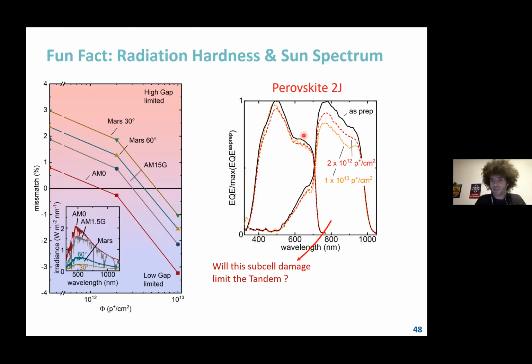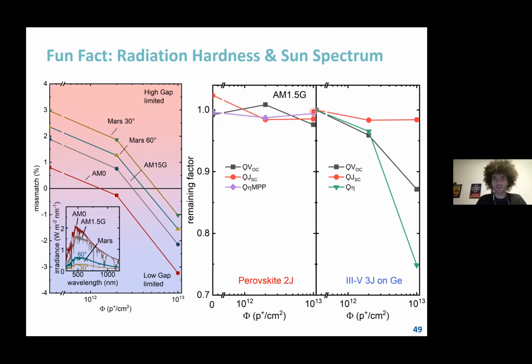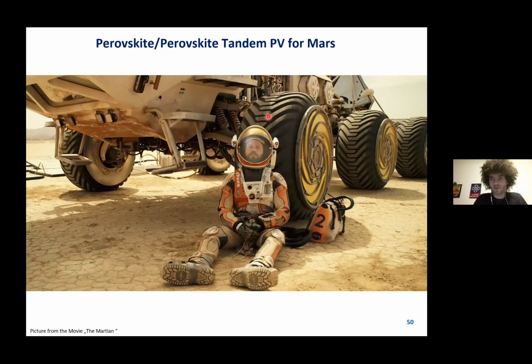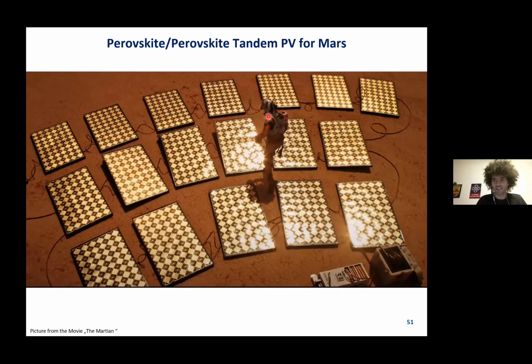So now when only one subcell degrades, this will of course become dependent on the illumination spectrum you have, right? And in the perovskite tandem case, we actually started with a device that was slightly current mismatched, limited by the high gap subcell under AM0. Under the Mars spectrum, for example, the device is very severely current limited by the high gap subcell. But as a result of that, the degradation of the low gap subcell almost vanishes. And I found this when looking at the device under AM1.5. So there we almost have no degradation in the perovskite. So I was thinking maybe our friend here on Mars would have been better off using perovskite tandems instead of these gallium arsenide triples.